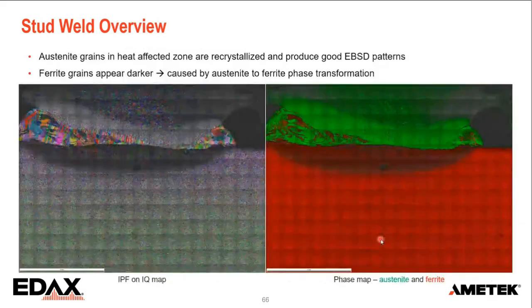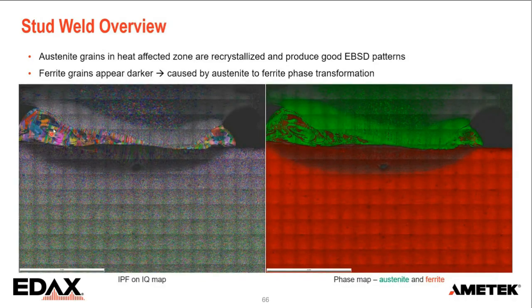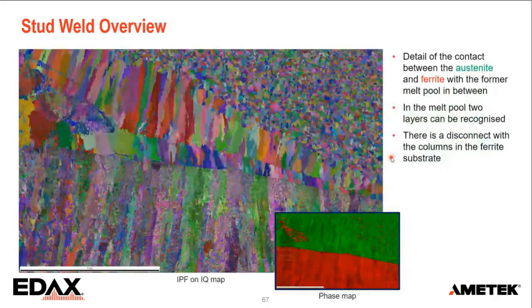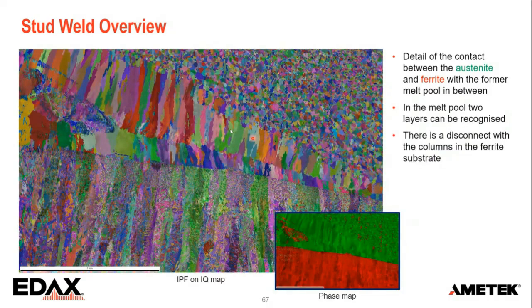Now, these are some of the maps. Here we can look at the small grain size. We can see those larger grains in the melt pool. And as you can see, most of that is green. That's austenite. And those darker swirls we have in here are ferritic. And when we then zoom in to an area close to the center of the weld contact, we can recognize the recrystallized austenite. And this is the melt pool. We have two layers of columnar grains. These are grown from both sides into the melt until those grains meet in the middle.